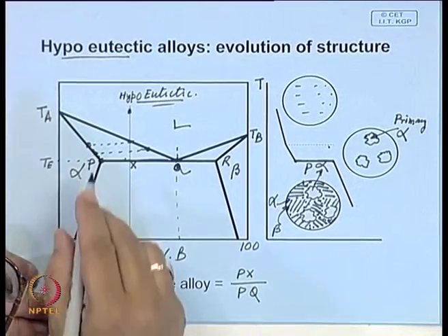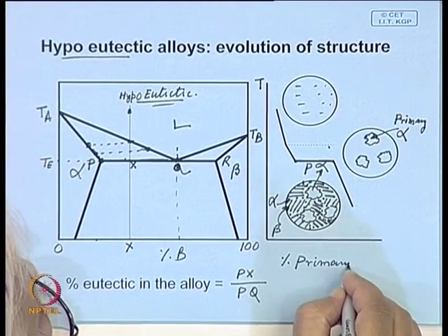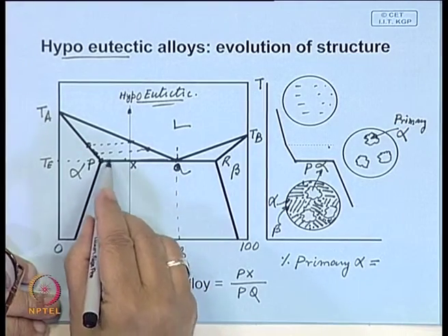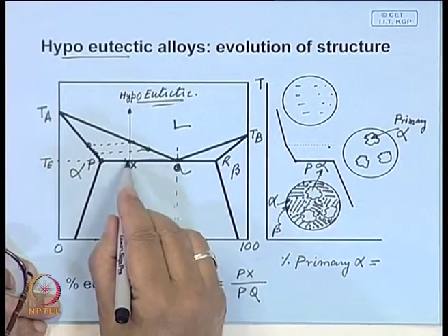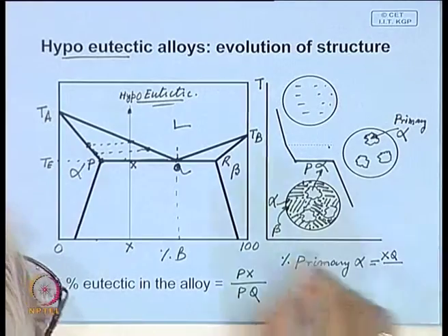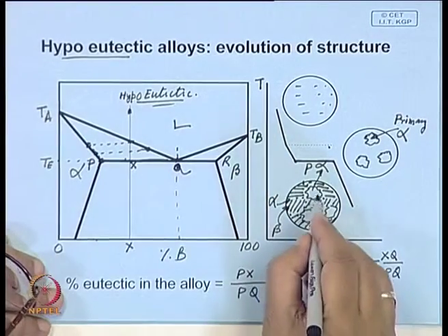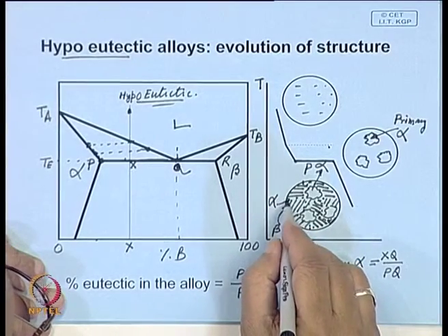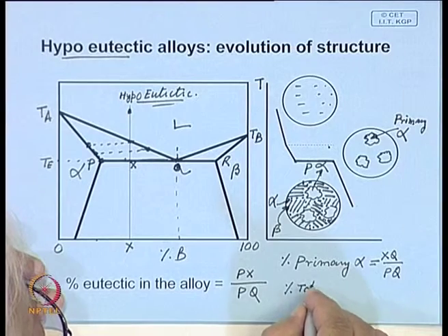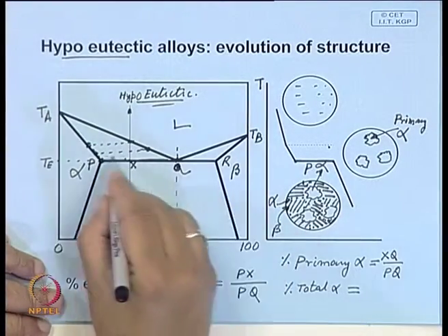And if you want to find out primary alpha, then percentage primary alpha is proportional to the opposite arm of the lever, that is xq over Pq. Now, look at this, you have alpha in two places, one as a primary alpha, and you also have alpha within the eutectic. If you want to find out percentage total alpha, which will be proportional to...